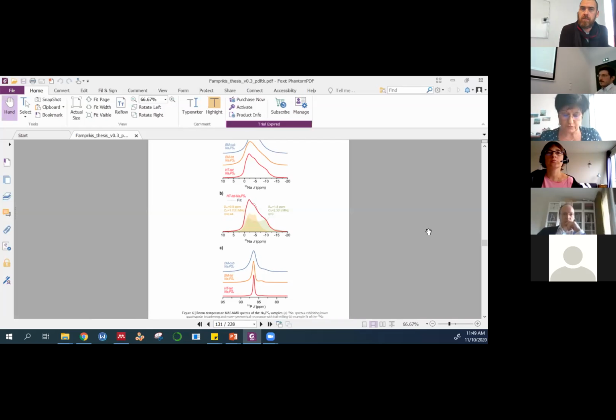So we come back to the discussion about the stoichiometry of your phase, because it's true that considering that you are doing this phase transition using temperatures, you are considering also phases prepared by ball milling. It is in fact not so obvious to consider that you have exactly the same stoichiometry for all the samples.